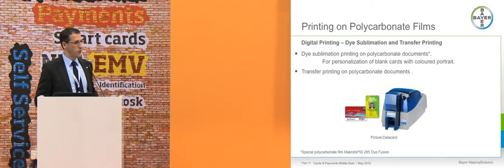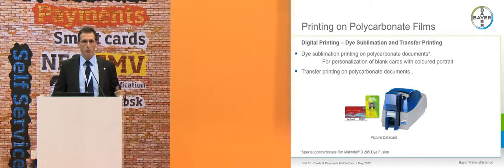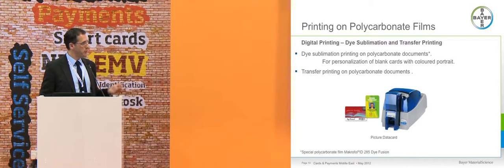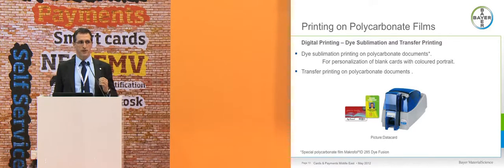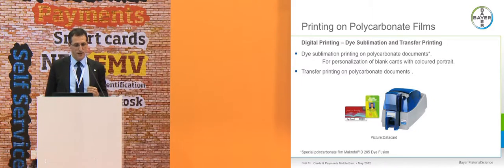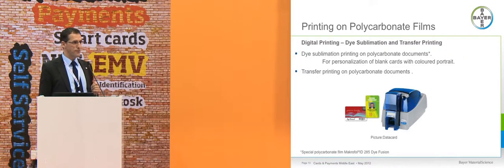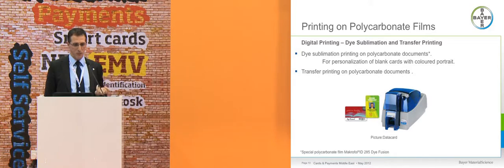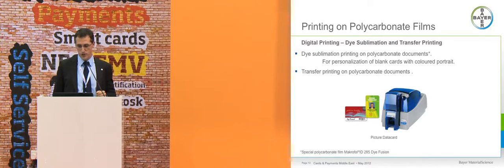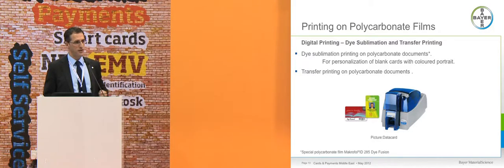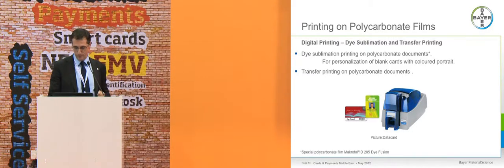If it comes to colored personalization by using dye sublimation printers, as seen in the picture, then special polycarbonate films are required from Bayer. These films are optimized for that printing process by having a functional layer on one side of them that will be compatible with the typical color ribbons used by that kind of printing machines.